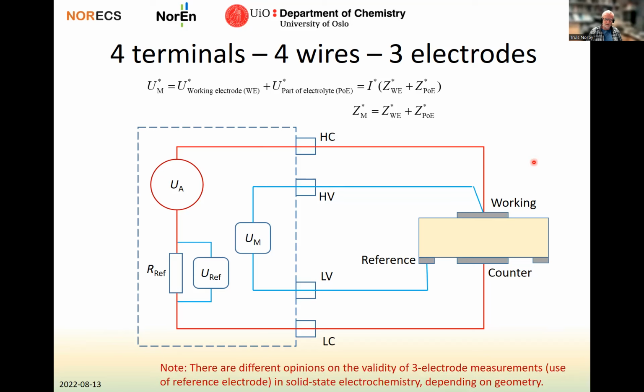You may note that there are different opinions on the validity of 3-electrode measurements and use of reference electrodes in solid-state electrochemistry, depending on this geometry. So this geometry that I show you here, the cross-section, is not fully accepted by everyone, and the exact measurement may vary depending on many parameters here.